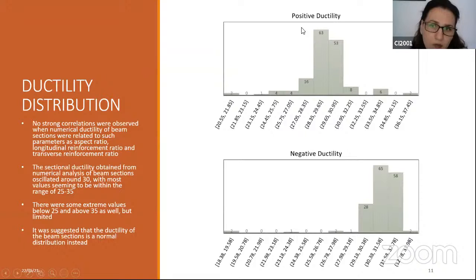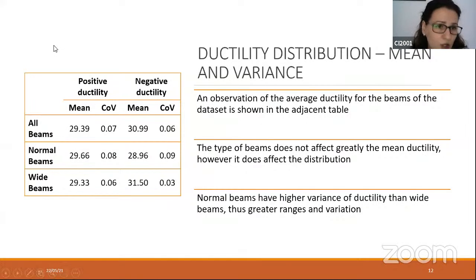So we thought that ductilities maybe could be observed as a distribution. So we plotted the histograms of positive and negative ductility values, and we can see that the histograms have quite a bell curve shape, especially the positive ductility, and a bit of a skewed bell curve shape in the negative ductility. So the ductility values for the beams are more of a normal distribution. And also, if we observe the mean values of ductility, both for all the beams and for normal and wide beams in separate data sets, we observed that the mean values were very similar for the positive ductility and also quite close for the negative ductility, and variance was very small as a matter of fact.